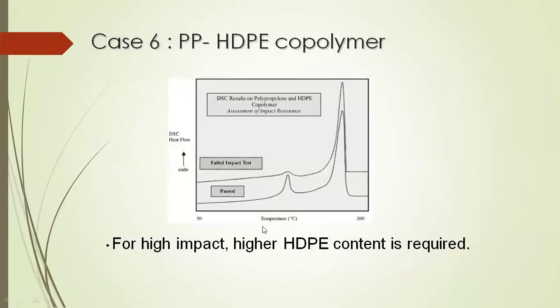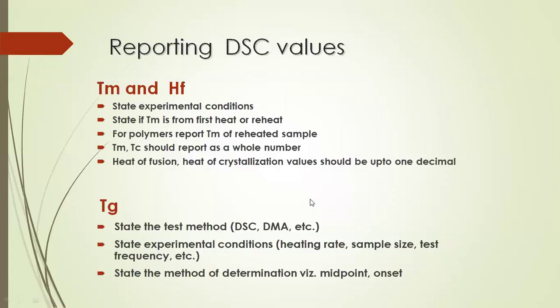Again, this is a problem where one batch was failing and one batch of PP was passing in QC. In PP, polypropylene, HDPE is always added to modify its impact. So one batch was failing, and when we did a DSC of that, you can see the HDPE content of the batch which passed was higher than the batch which failed. Just one DSC told us why the batch is failing, because the HDPE content is different. Now you can find out the small HDPE percentage using DSC. Because in TGA, you will not get this difference, because we have seen that PP and PE degrade at the same temperature. No change in TGA, but in DSC you see it in the melting temperature and the content also.